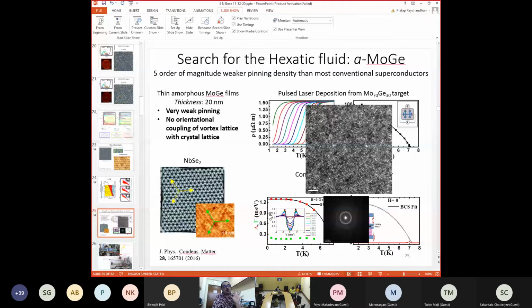We performed detailed experiments on the orientation of the vortex lattice, and whether with magnetic field the orientation changes, whether the vortex lattice rotates and so on. What we realized is that the vortex lattice orientation has a very strong coupling with the underlying crystal orientation. The stable state of the vortex lattice is always aligned along the principal direction of the crystalline lattice. So this is imposing an orientational order. You can of course realize metastable states where the vortex lattice is misoriented with respect to the crystal lattice, but you can shake them, and the moment you shake them, they will undergo a transition into this oriented state. So this is an additional complication that we did not want to have.